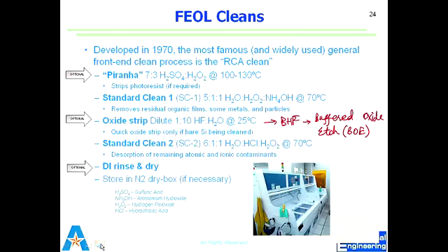So, of course, it's going to neutralize essentially when the whole hydrogen peroxide is used up, but you have much more sulfuric acid to do that reaction. So you have many more sulfuric acid that doesn't react, but the whole reaction is very aggressive, much more aggressive. The standard is what the book says, 7-to-3. We use 1-to-1, 1-to-2, 1-to-3, many different ratios.